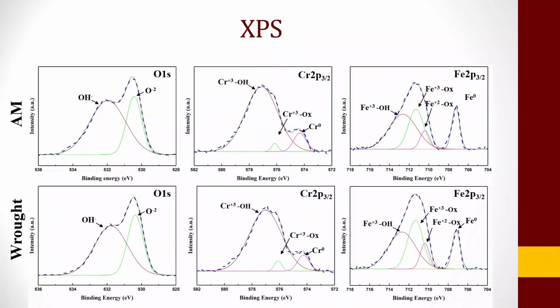So let's move on to the XPS analysis. So again, it basically tells you the detailed surface chemistry, including if the metals are in the elemental state or if they are in the oxide forms and so on and so forth. So when we look at the additively manufactured and the wrought oxygen, chromium, and iron high resolution spectra, they are pretty much the same, except that sometimes we do see a little bit of extra oxide formation on additively manufactured samples.